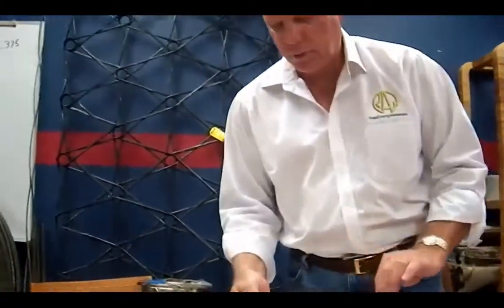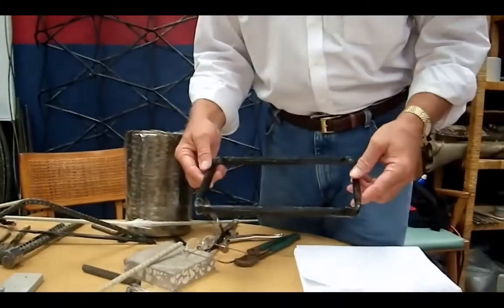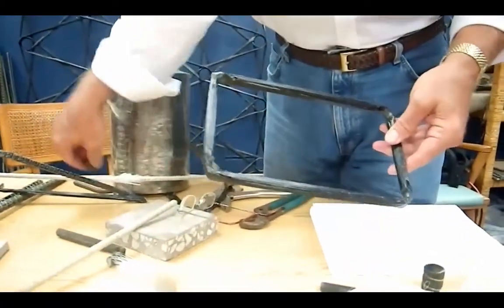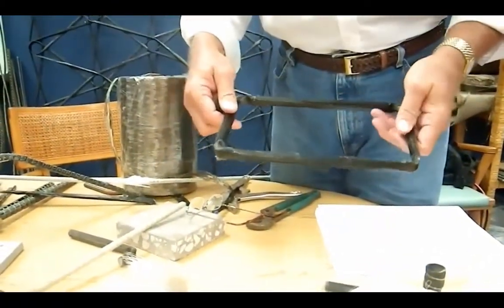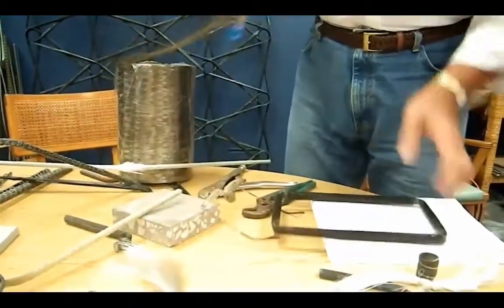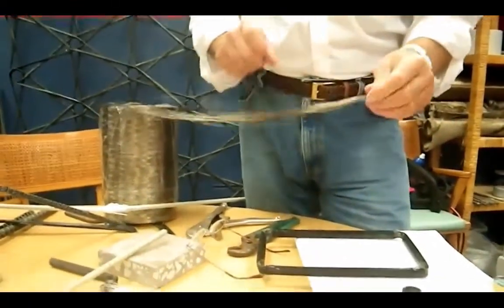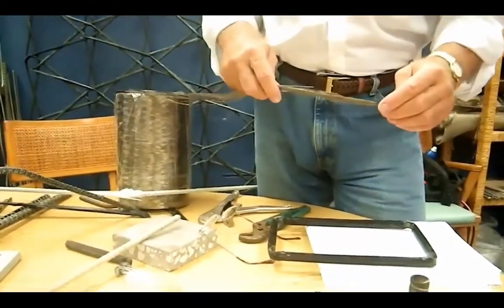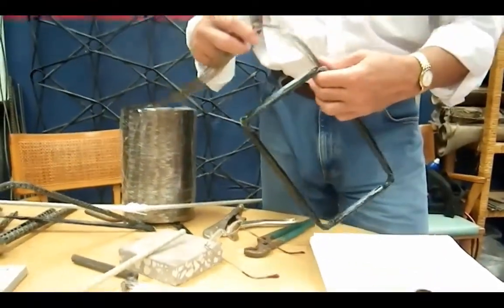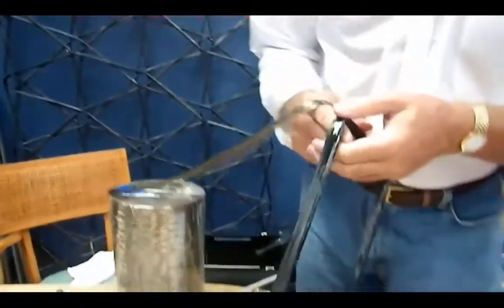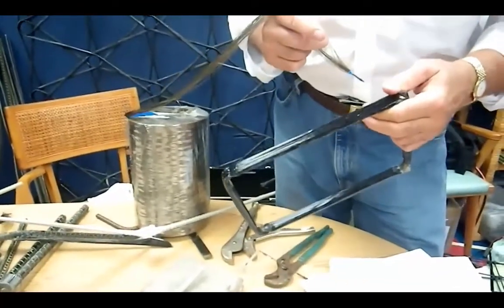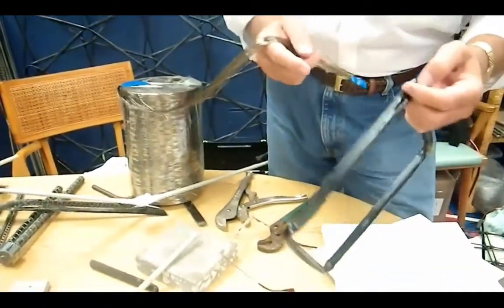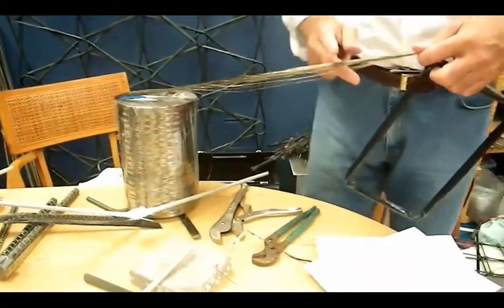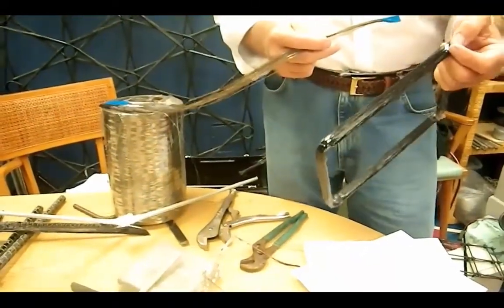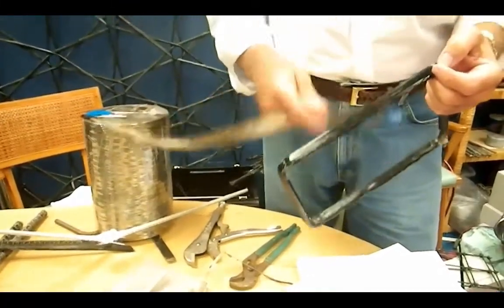This one happens to be, I think, for 25 millimeter, just a little 6 by 10 cage for some beam somewhere. We take the roving as it is in this state, and it's coated through one of the high-speed coaters, and it goes on a set of forms, pins, and it's wound around the pins. Really simple in principle, very difficult to do at high speed. We are able to put a stack of rovings around these pins to produce these stirrups to get whatever strength it is that's required for the application.